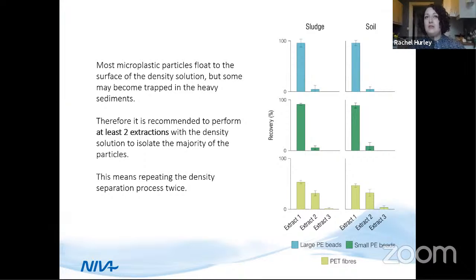So when we're using these density solutions, we're using densities that will extract the microplastic particles. And so they should all float to the surface of the solution when we undertake this process. But if you have a complex sample, some of them may get trapped in those heavy sediments, even though you've agitated, just when they're settling out. Therefore, it is recommended to perform at least 2 extractions with the density solution to isolate the majority of the particles. This means repeating the process that I've just described twice in order to make sure that you are recovering the majority of the microplastics in your sample.